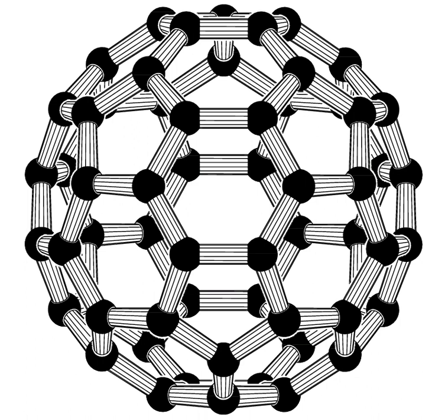This is especially important when it is necessary to graft chemical functions to the surface of the nanotubes, functionalization, to add properties to the CNT. Covalent functionalization of SWNTs will break some C=C double bonds, leaving holes in the structure of the nanotube and thus modifying both its mechanical and electrical properties. In the case of DWNTs, only the outer wall is modified.